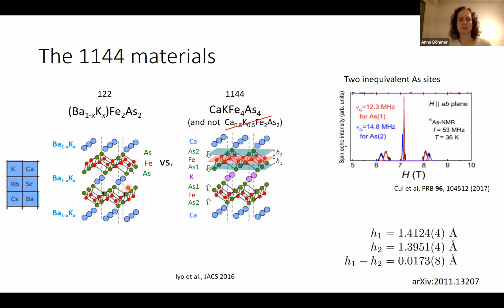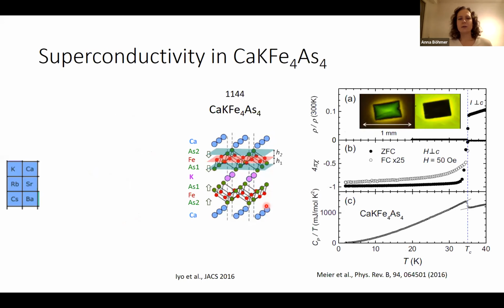So we lose the central symmetry. We of course are still centrosymmetric, but we lose the I4/mmm from this one, and we end up with a P4/mmm. The 1144 pure is a beautiful superconductor, 35 Kelvin. So this is single crystal data from the Canfield group.